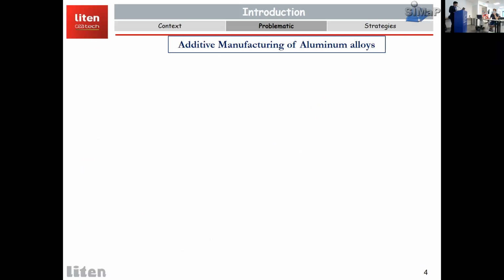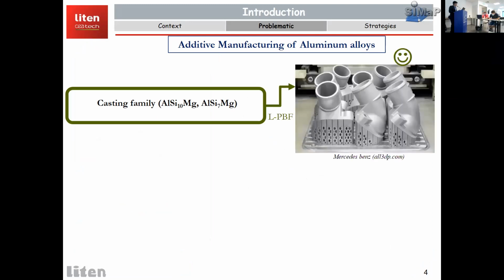So now if we are looking into the additive manufacturing of aluminum alloys, for example, the casting family, which is the most used in additive manufacturing of aluminum alloys, like the AlSi10Mg and AlSi7Mg, for instance. So if we do L-PBF of these particular alloys, it's very easy to process, and you can get complex structures, you can get complex parts directly out of it.